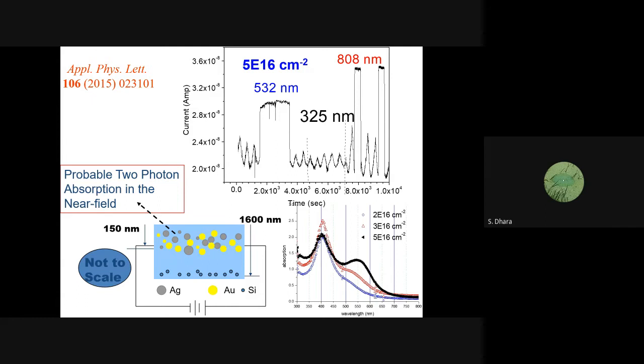You can do the ion milling. We did the ion milling of both sides of these facets, and then we made the metal contact here. You see that this is a cross section image, not a top view. It has gone to the depth of the system, and silver and gold nanoparticles are somewhere in between. Here you can ask the question: for silver you said 400 nanometer is the resonance, but interestingly second harmonic generation was stronger than the primary, and that's what this paper is all about. Even the localized interaction is so strong that you can generate second harmonic.